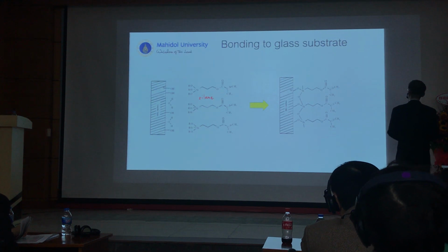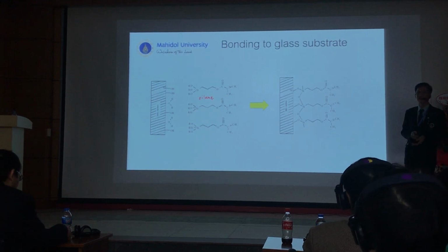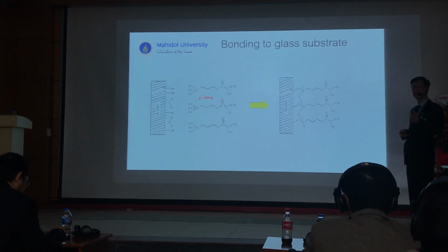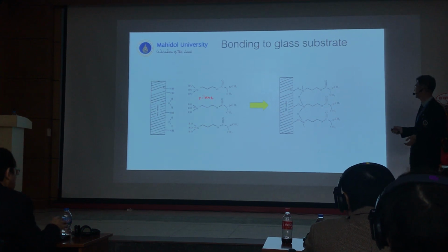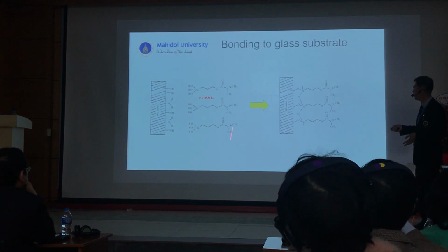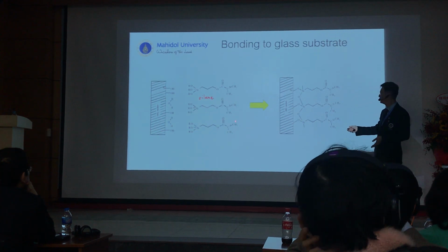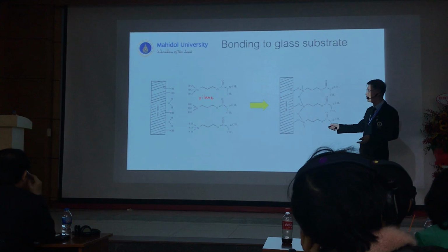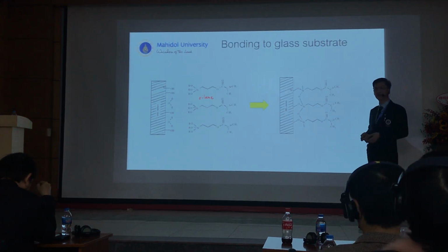And the problem with the zirconia is that when you try to bond the zirconia, it's very hard. But if you want to bond something like glass, like e.max or porcelain, we just etch it, apply silane on the porcelain, and bond it with resin cement. So it's easy. Because of silane, one side is a polymer, going to contact the polymer in the resin cement, and one side is going to bond to the glass or silica in the porcelain.